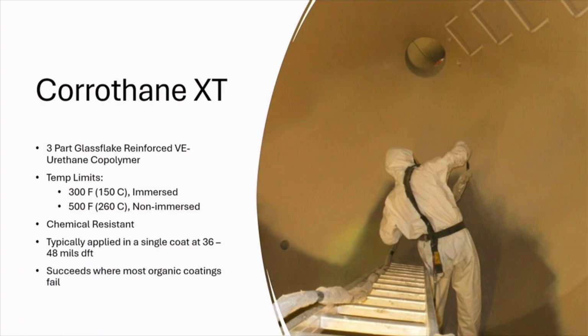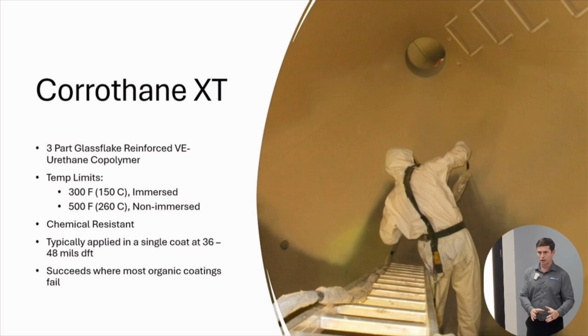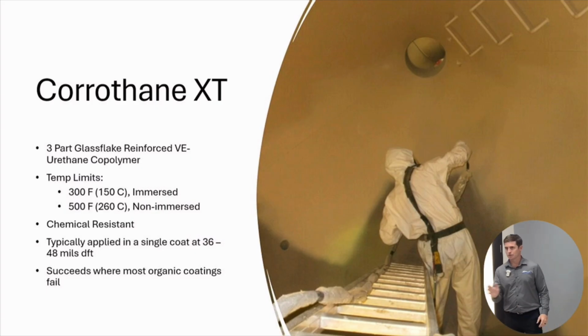Corrothane XT. There we go. I've got C on here. 150C, 260C. So the Corrothane XT works a little differently. You actually have to mix it. It's a step-down mix. So you mix in the urethane and the urethane diisocyanate, which will catalyze the urethane. You let that sit, and then you mix in the MEKP, the organic peroxide, which catalyzes the vinyl ester. You step that and you time it.